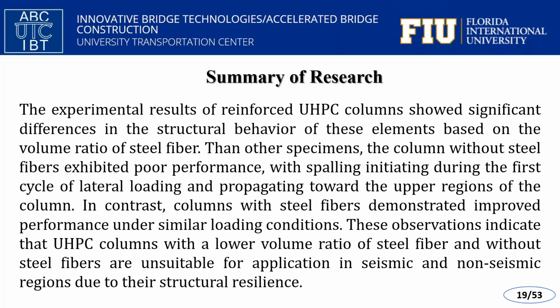The experimental results of reinforced UHPC columns showed significant difference in the structural behavior of these elements based on the volume ratio of steel fiber. The column without steel fiber exhibits poor performance, with spalling initiating during the first cycle of lateral loading and propagating toward the upper region of the column. In contrast, columns with steel fiber demonstrate improved performance under similar loading conditions. These observations indicate that UHPC columns with a lower volume ratio of steel fiber and without steel fiber are unsuitable for application in seismic and non-seismic regions due to their lack of structural resilience.